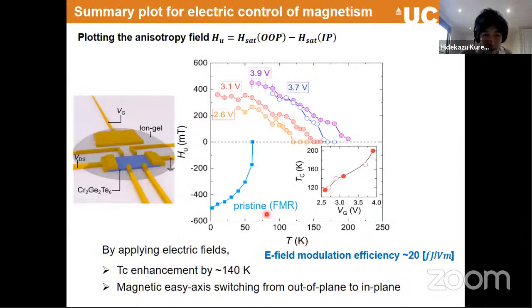Okay, so this is a summary. What we plot is the saturation magnetic field for out of plane and in plane, and if you subtract these, that should be related to the anisotropy field. So that's a plot as a function of temperature. What we can tell is that as soon as we dope by electric field, you can significantly increase the Curie temperature on the higher temperature side. And if you keep doping, we can also notice that this carrier doping can promote both magnetic anisotropy and the Curie temperature on the upper side.